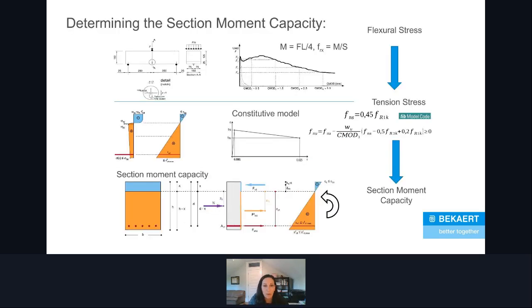Now, if we bring this around a little bit, go a little bit deeper here, there's a European test that's very similar to the C1609 test. It's the EN 14651 test. The main difference between them is that this has a notch at the center of the beam, and this is measuring crack mouth opening rather than vertical displacement. So the curve that you see in the top center here is a sample of what you might see with this.